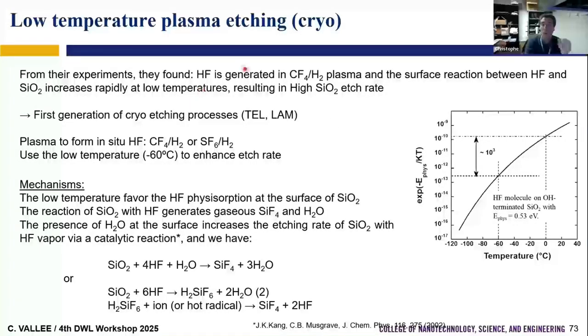So they said that when we do CF4/H2 plasma, we form HF because we dissociate CF4 in CF3 plus F. We dissociate H2 in H plus H. So H atom will react with F to form HF. HF will go to the surface. And remember, if we go to -60, which is why I did this calculation, if you go to -60, you will increase by 1,000 the lifetime of HF molecule on the surface. And so if you have more HF, when you add the ions, if you have more etching agent on the surface, you will promote and enhance the etching.